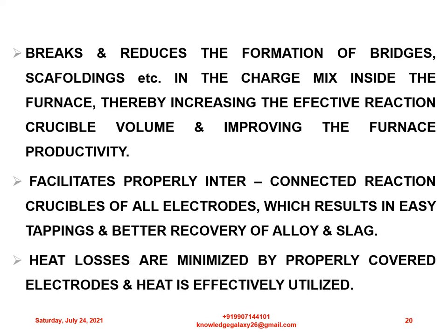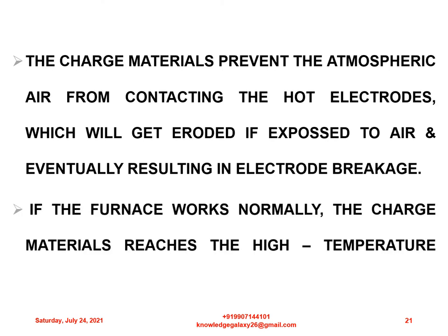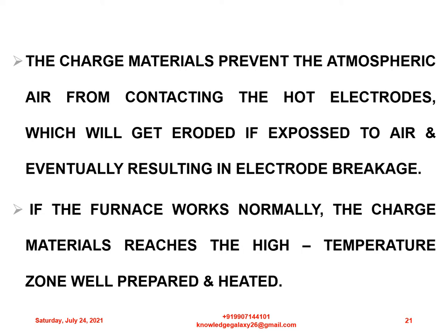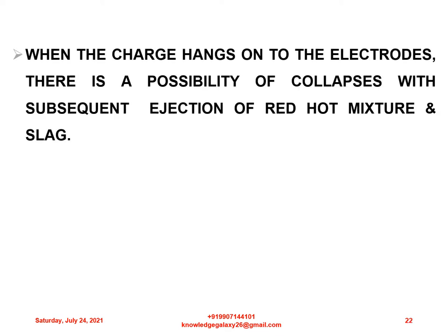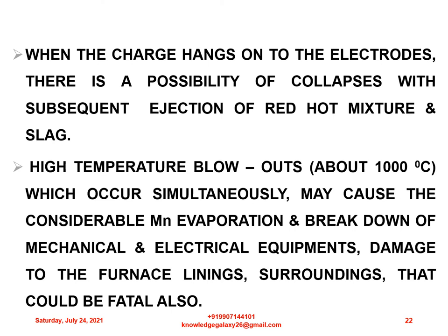Heat losses are minimized by properly covered electrodes, and heat is effectively utilized. The charge materials prevent atmospheric air from contacting the hot electrodes, which would erode them if exposed to air and eventually result in electrode breakage. If the furnace works normally, the charge material reaches the high-temperature zone well-prepared and heated. When the charge hangs onto the electrodes, there is a possibility of collapses with subsequent ejection of red-hot mixture and slag. High-temperature blowouts at about 1000°C, which occur simultaneously, may cause considerable manganese evaporation and breakdown of mechanical and electrical equipment, damage to the furnace linings, and damage to the furnace surroundings — which could be fatal also.